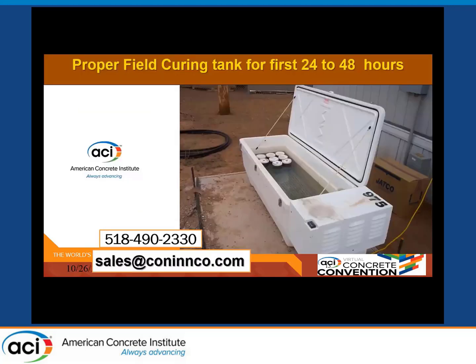Now this is a thermal tube curing box. This is one of our boxes that I had with Gallup Sand and Gravel about 20 years ago. You had the water in there. It kept the cylinders at 73 degrees. Yes, it cost me a few $1,000s at that time, but it was cheaper than tearing out concrete because the cylinders weren't properly cured and you were going to be blamed for it. The only problem we had with some of these boxes is that test labs would not take their cylinders and put them in there because it was too far to set them up, because the box has to be set up where you have power. Next slide.